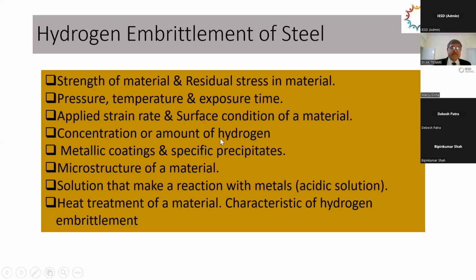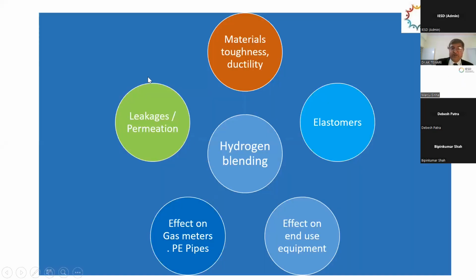And certain solutions react with the metals, like acidic solutions, which I prefer to avoid. And heat treatment of the material. Nitrogen, particularly nitriding, improves the embrittlement properties. There won't be more embrittlement if you are using nitriding as a heat treatment process. So we summarize the problems here: material toughness, ductility, elastomer effect, because we are trying to distribute through a pipeline system which has PE pipe too, leakage, permeation, effect on the pipes and the meters, and of course end use burners and others, what effect you are having. Next slide, ma'am.